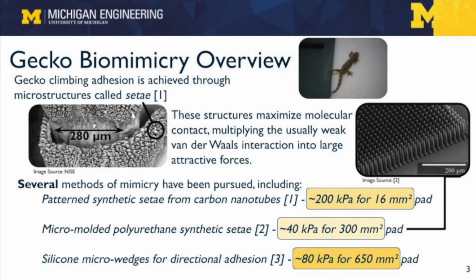However, it's clear from these very similar approaches that the two adhesive pads with the largest area actually have the smallest shear stress capacity. This would indicate that as you add more area to the pad, the area you add helps increase the force capacity less and less, and so the shear stress capacity falls. This is known as inefficient scaling.